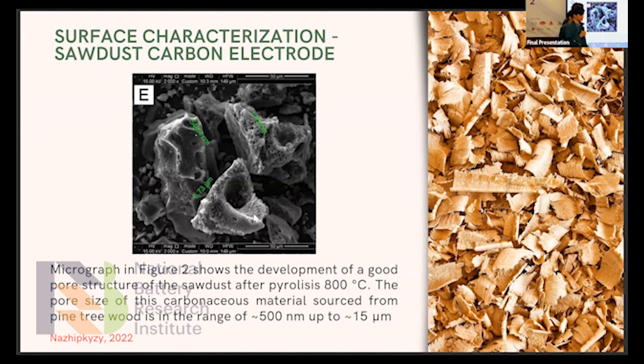One more question. Okay. So your biomass here is actually from the wood, sawdust. The sawdust is actually coming from the biohydrometallurgical lab. So it's actually from manufacturing, and we utilize it to be the carbon electrodes. First of all, it's already in small pieces, and then you clean it by soda. After you have the sawdust, you clean it by hydroxide, the impregnation stage. What's the molar of the hydroxide? Four molar. And how long? For about 1 day. So you soak it in 1 day.